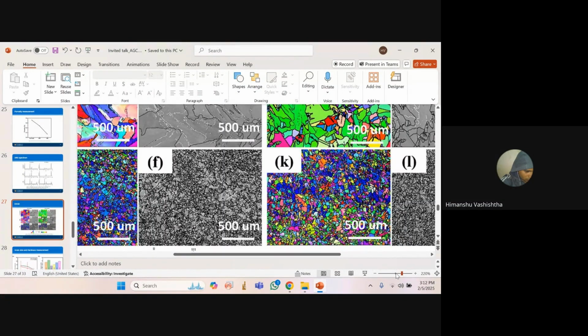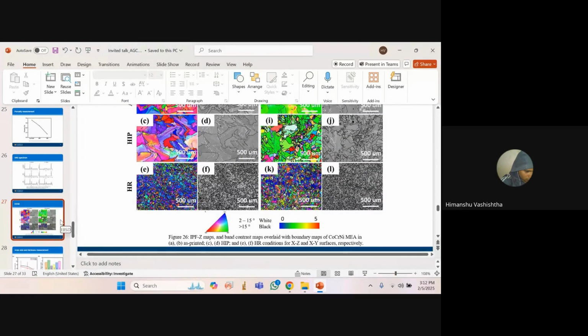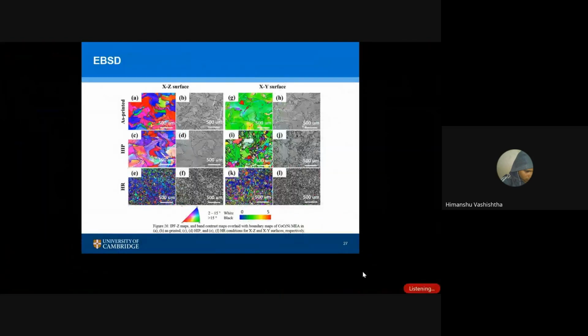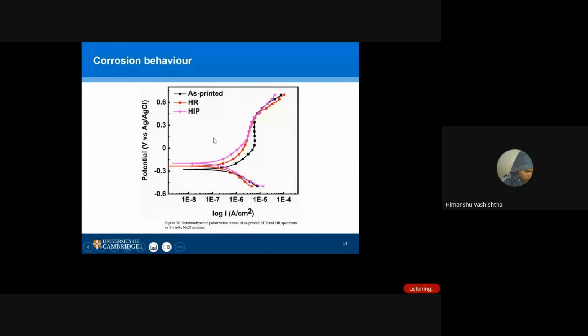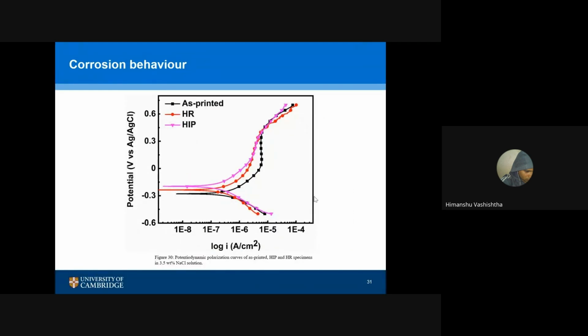And if anyone has the basics of corrosion, they know that if higher grain boundaries are there, those grain boundaries are acting as a defect. So with a high number of grain boundaries, a high number of defects will be there, and subsequently lower corrosion resistance, even though it's better than the as-printed case. The hot isostatic pressing has the lowest number of defects and moderate grain boundaries among all three, so in that way it's having the best corrosion resistance.